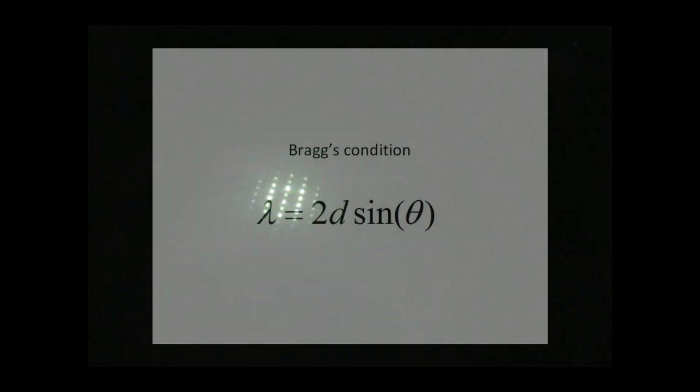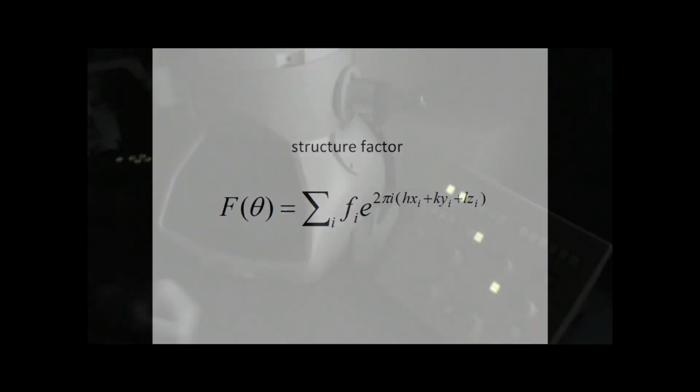Let's now talk briefly about one of the most important capabilities of the TEM, to produce diffraction patterns. When an electron interacts with the potential of an atom in a crystal lattice, it can be diffracted. Electrons will diffract in all directions, and because of the electron's wave-like behavior, a diffraction pattern will arise. As it turns out, whenever the distance between planes of a crystal with respect to the angle of the incident beam is equal to a multiple of the wavelength of the electron, constructive interference occurs and the diffraction along that direction is the strongest. Conversely, electrons diffracted in other directions will experience destructive interference. This is the origin of the diffraction patterns observed in the TEM.